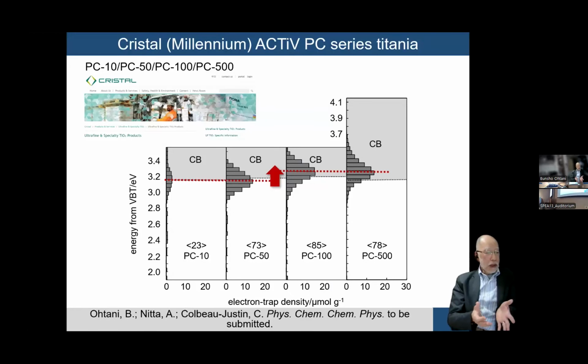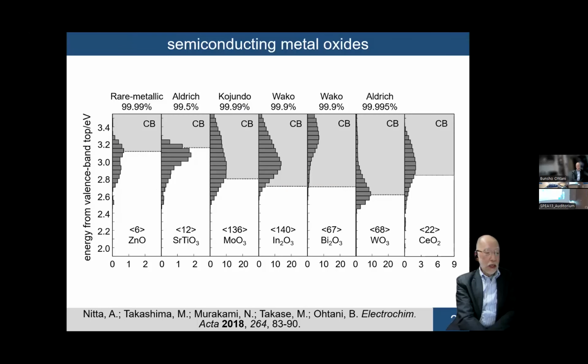Probably you know the previous Millennium Inorganic Chemicals titania, the PC series. I understood that PC10, 50, 100 and so on have almost the same structure, with only the particle size different. However, checking this ERDT pattern, there is a difference between PC50 and PC100. That means they have different sizes and different specific surface areas, but also the surface structure is a bit different. So depending on the size of the material, the surface structure is a bit different.